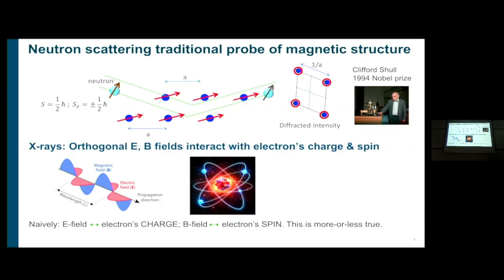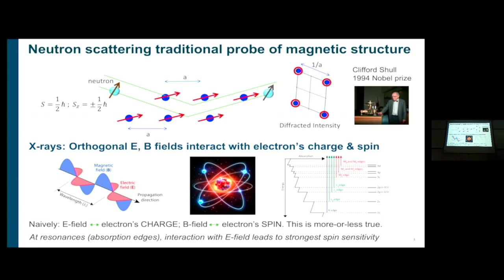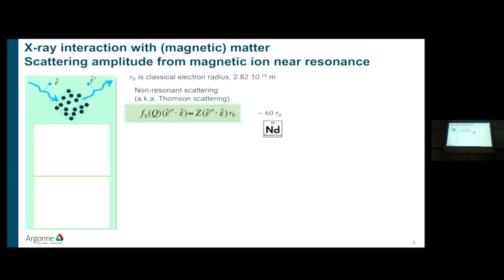And when you think about X-rays, X-rays have orthogonal electric and magnetic fields that oscillate, it's an electromagnetic wave, and these fields interact with the electron's charge and spin. So naively, you would think that the electric field of the X-rays will couple to the charge, and the magnetic field will couple to the spin. And that is more or less the case. But what we'll see today is that the sensitivity to magnetization comes predominantly, and is pronounced, by coupling to the electric field, not the magnetic field. And that happens at resonances when you tune the X-ray energy to near absorption edges, electronic transitions in an atom. So that's what leads to the strongest spin sensitivity. And I want to walk you through some of these fundamentals at a very high level.